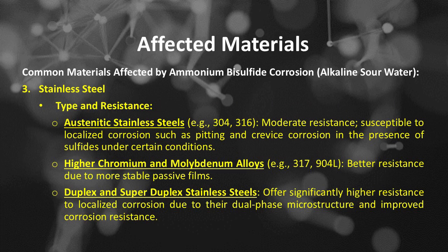Common materials affected by ammonium bisulfide corrosion or alkaline sour water, number 3, is stainless steels. Type and resistance of stainless steels include austenitic stainless steels such as 304, 316: moderate resistance, susceptible to localized corrosion such as pitting and crevice corrosion in the presence of sulfides under certain conditions. Higher chromium and molybdenum alloys such as 317, 904L: better resistance due to more stable passive films. Duplex and superduplex stainless steels offer significantly higher resistance to localized corrosion due to their dual-phase microstructure and improved corrosion resistance.